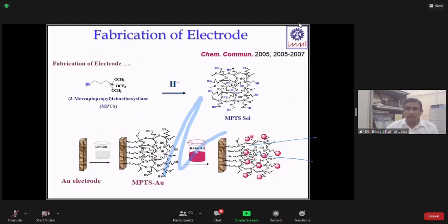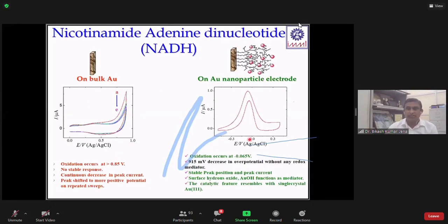To do that, you have to make a self-assembled metal nanoparticle layer on the electrode surface. So we developed this method: three-mercaptopropyl trimethoxysilane, this is a molecule. We do some hydrolysis and condensation process to make a three-dimensional network. Then you do the self-assembly on the gold electrode surface. Then you self-assemble the nanoparticle by dipping it in the gold nanoparticle solution, because there are a lot of thiol groups, that's why it gets attached to the gold nanoparticle. So this gold nanoparticle-modified sensor has been developed.